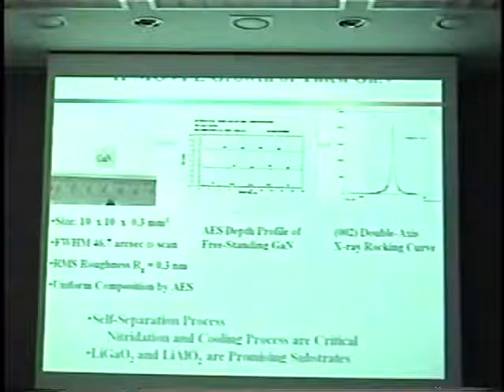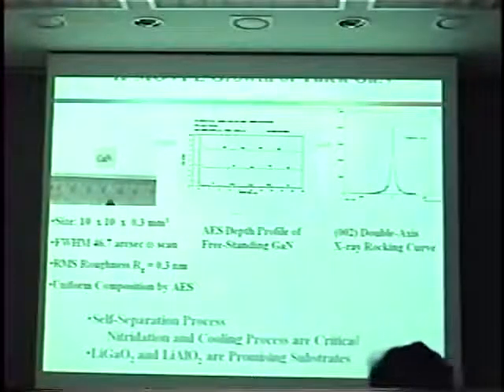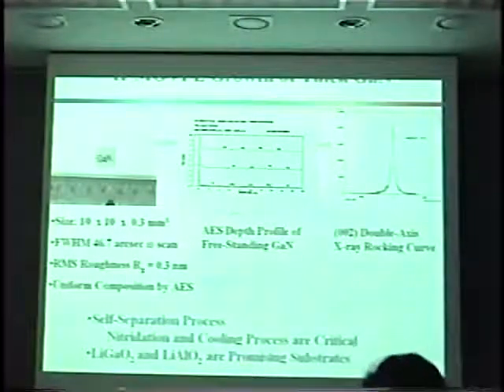What's really interesting is it's self-separating. That is, when we cool in the reactor, the LGO with thick gallium nitride on top of it, we would pull it out, and the gallium nitride would be freestanding, and you just lift it right off. Looking at both sides of the gallium nitride, it was separating between the oxynitride buffer layer and the gallium nitride grown by MOVPE, which allowed reuse of the relatively expensive LGO substrate.